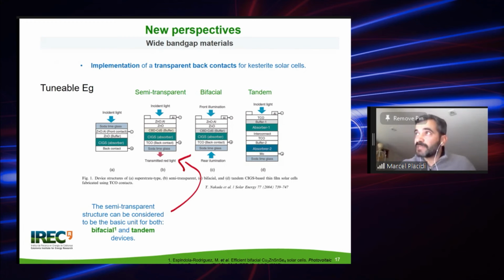Another advantage of thin film materials, and in particular of chalcogenide thin films, is the tunability of the band gap of the absorber. This is possible with kesterite, with chalcopyrites, and also with many other chalcogenide absorbers, which involve sulfur and selenium, and also telluride. This band gap tunability is particularly interesting when it is combined with a transparent back contact. This allows the fabrication of new kinds of devices which are not feasible, for example, with silicon. We can fabricate semi-transparent devices, as you can see there, with a transparent back contact, which are also bifacial devices, which can be illuminated from front and back.